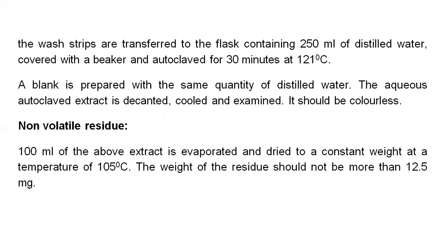A blank is prepared with the same quantity of distilled water. The aqueous autoclaved extract is decanted, cooled, and examined. It should be colorless. Non-volatile residue. 100 ml of the above extract is evaporated and dried to a constant weight at a temperature of 105 degrees Celsius.